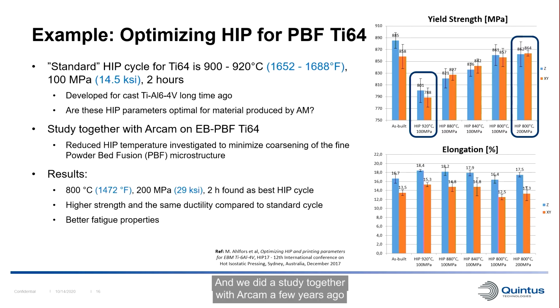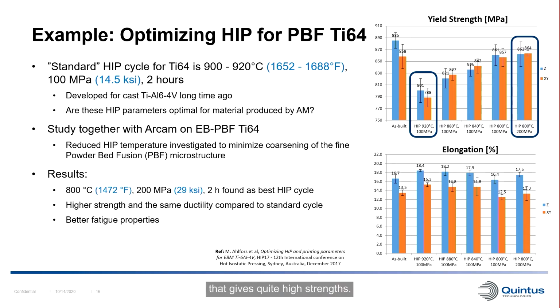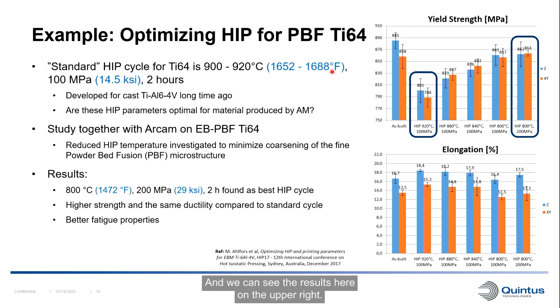We did a study together with Arcam a few years ago to look at whether different HIP parameters could lead to better properties. Our approach was looking at lower HIP temperatures to try to minimize the coarsening of the fine microstructure that we have in the powder bed fusion material, which gives quite high strengths. And we can see the results here on the upper right.